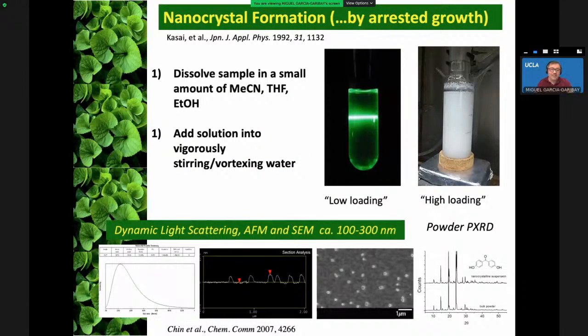It was actually developed by Kasai and Nakanishi in Japan in 1992. The idea is to dissolve the sample, your molecule, in a small amount of a water-soluble solvent, for example, acetonitrile, THF, or ethanol, and add that solution into vigorously stirring or vorticing water. So when we have low loading, we have transmission of light, and we can do spectroscopy. When we have high loading, we can do photochemistry. We can determine the characteristics of our nanocrystals by using dynamic light scattering, atomic force microscopy, scanning electron microscopy, or we can centrifuge our crystals and collect them to get a powder X-ray diffraction pattern.